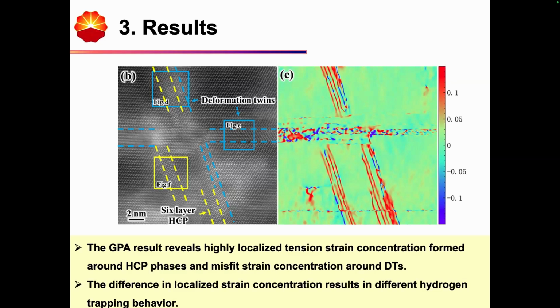Therefore we apply some GPA analysis, and we can say that for the HCP phase, it will cause some tension concentration, and this tension concentration will cause expansion of the lattice, which causes localized hydrogen concentration.